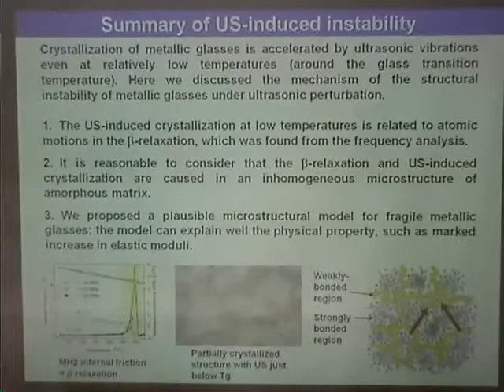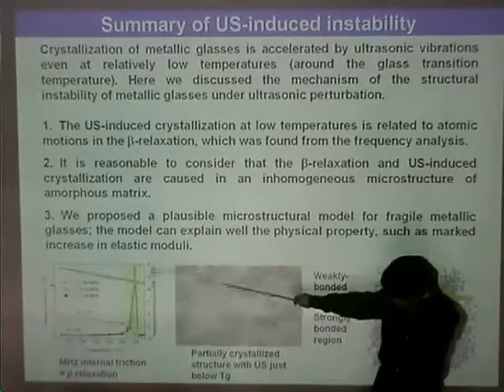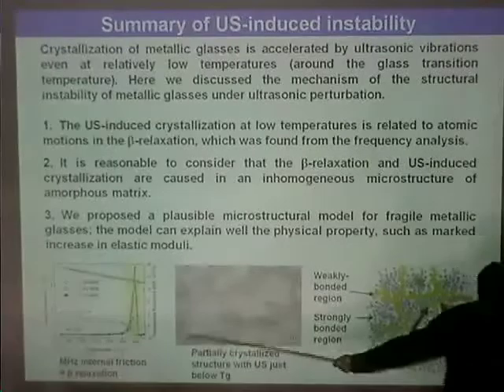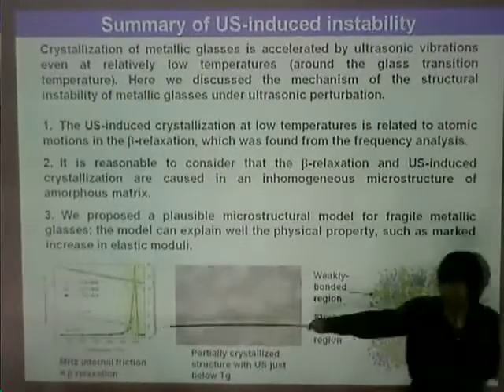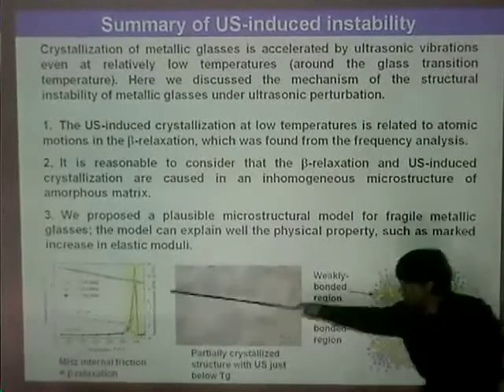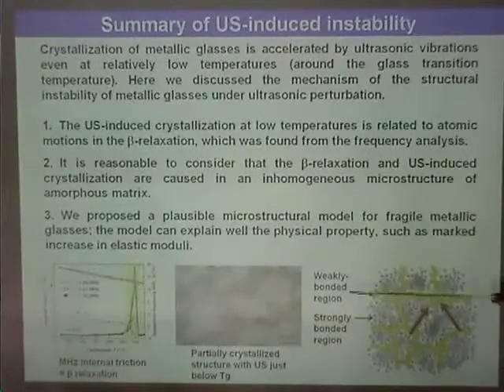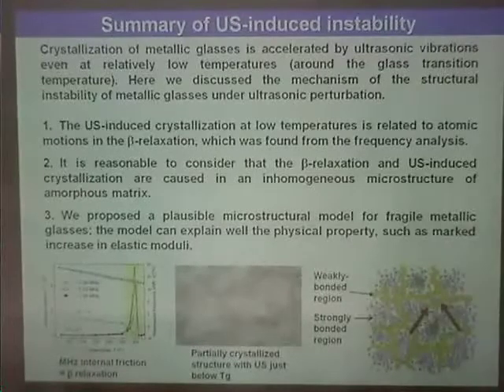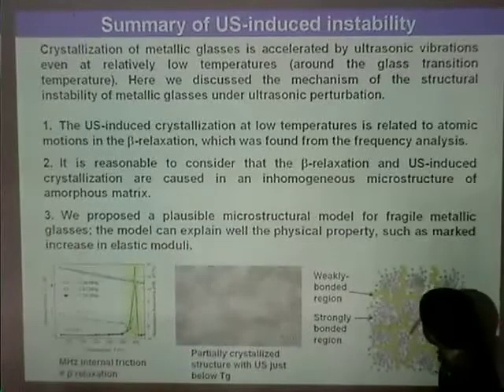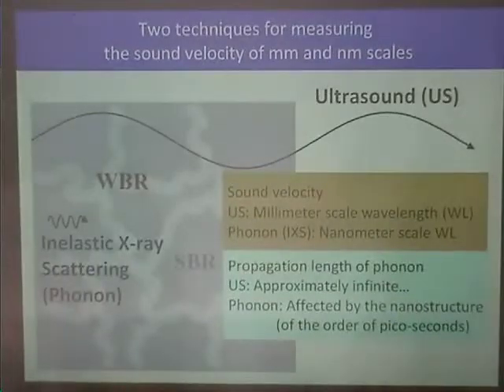Okay, so in summary, beta relaxation of 1 megahertz occurs around the glass transition temperature, and this beta relaxation leads to the crystallization of some part of the metal glasses. Then we propose this microstructure. In order to demonstrate the validity of this nanostructure, we have employed inelastic X-ray scattering (IXS) measurement and ultrasonic sound velocity measurement.